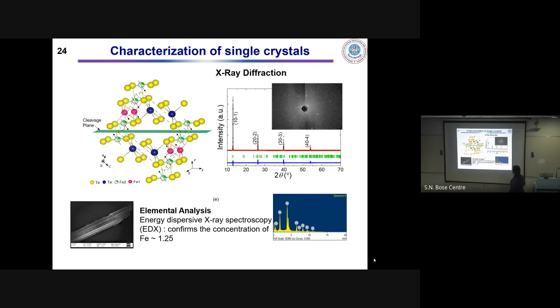First, I would like to give the characterization of the sample from X-ray diffraction. The peaks could be identified as the (1, 0, -1) Bragg peak, and from energy dispersive X-ray spectroscopy we could confirm the concentration of iron to be 1.25. This is very important in this sample because the iron concentration determines the TN. From the TN we observe, as well as from the index, we could confirm it is very close to 1.25.